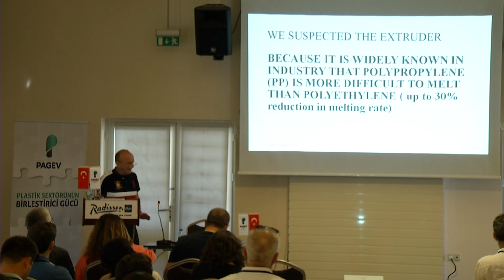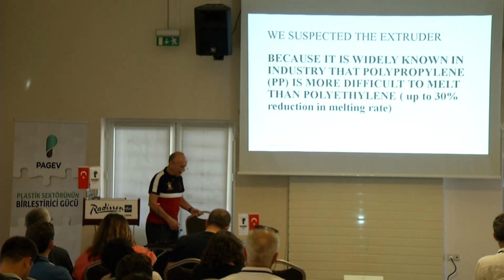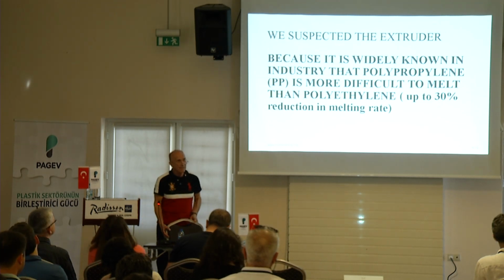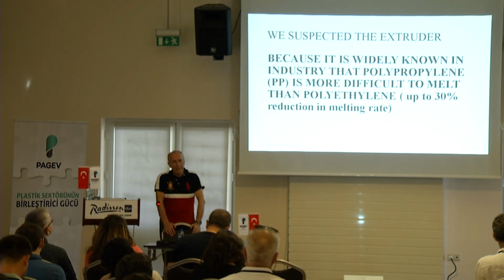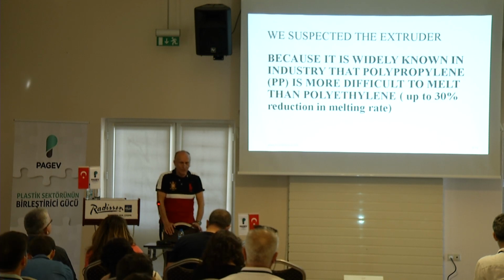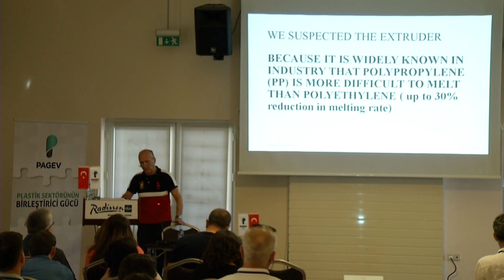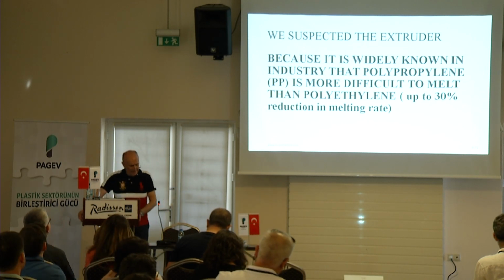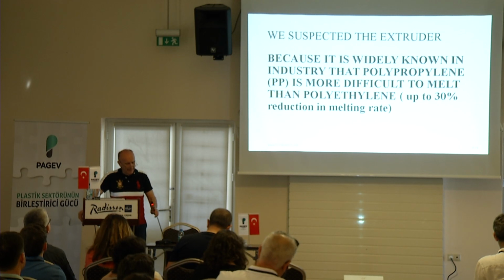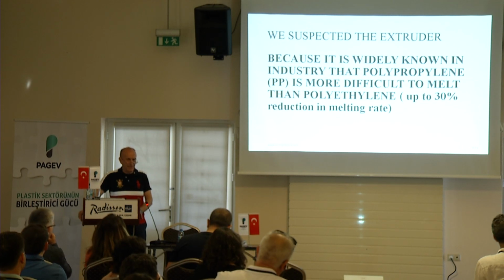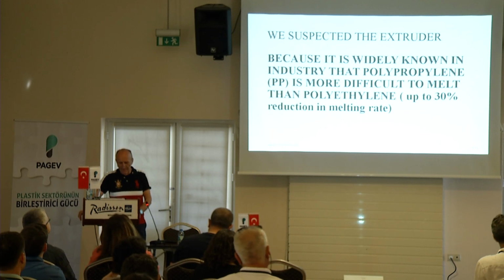because what is known in industry in general is that polypropylene melts about 30% less than HDPE under the same conditions. And I'm not really sure why. We did some work, might take another look at it, but I'm not quite sure why. But the net result is that polypropylene is rather difficult in melting. And so we wanted to see what really happens.